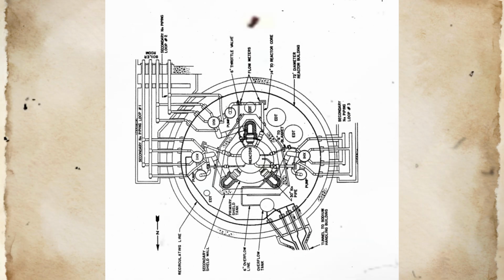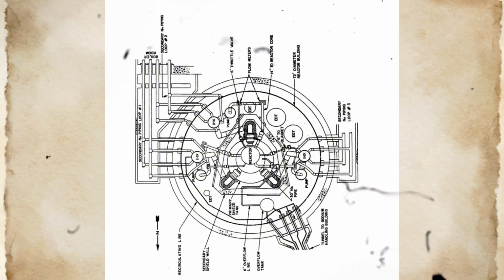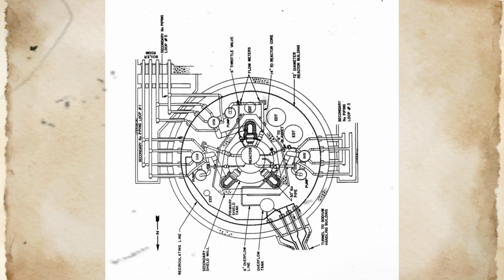suggesting that the termination of nuclear fission and reduction in heat generation rates had stabilized thermal conditions sufficiently to prevent continuing fuel damage. However, the monitoring also showed that fission product release continued at levels well above normal background, confirming that damaged fuel remained in contact with the sodium coolant and that some degree of ongoing interaction between damaged fuel materials and the coolant system was continuing.